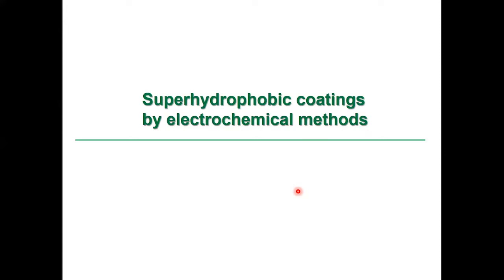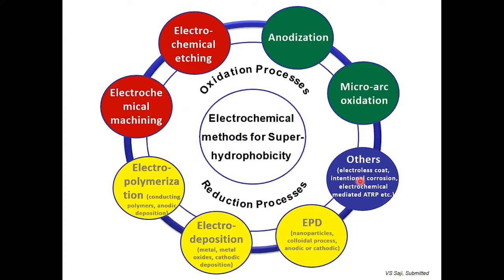So we can see the methods employed for superhydrophobic coatings, electrochemical methods for fabricating the superhydrophobic coatings. What are the methods? So see this scheme. In electrochemistry we have either oxidation process or reduction process. If you see the two green, they are called anodization and micro-arc oxidation. They are typical oxidation processes for making thick oxide layer on metallic surfaces. Anodization and micro-arc oxidation are usually performed at a higher voltage. So these are the two oxidation processes that can make a superhydrophobic surface.